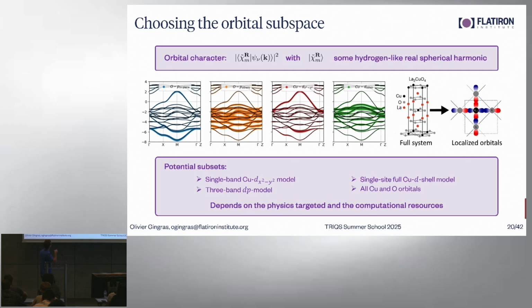I can also say, well, actually this model is not sufficient. I want to include these oxygens because they hybridize directly, right? So then I could use as my set these in-plane orbitals with this one, a 3-band model, and I can think that this is going to be better physics. I can also say, well, actually, I don't think the oxygen is useful. I think the local interactions are much stronger. So these orbitals, although they're not occupied at the Fermi level per se, they're pretty close. So maybe I want to do a 5-orbital calculation on my copper. That's another option.